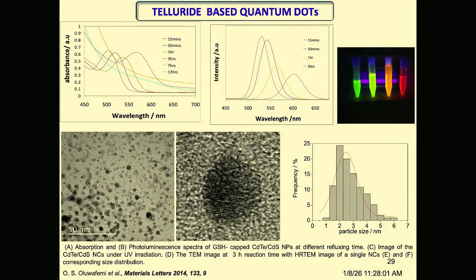So this is the characterization that we did. We can see after 3 hours. This is what I mean by size dependent. The one that is fluorescing in the green is the smallest. It's about 1 nanometer. By the time it gets here, it becomes 1.5. By the time it's in orange, it becomes like 2.5. But by the time it's red, it's about 3 nanometers. And that's what we need, because we want something that can fluoresce in the red region so that we can identify the cells that are in the body. And this is the microscope that I talked about. This is about 3.5 nanometers.